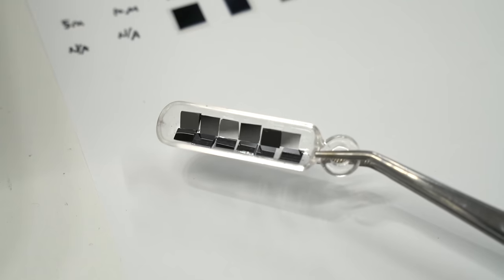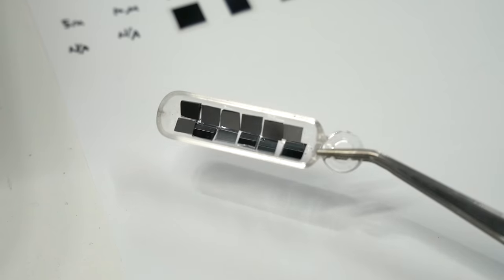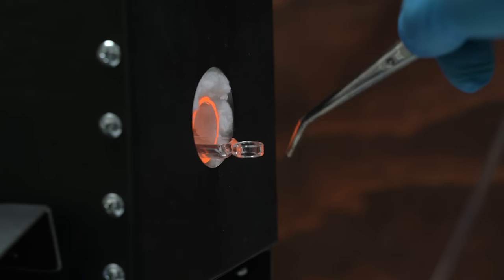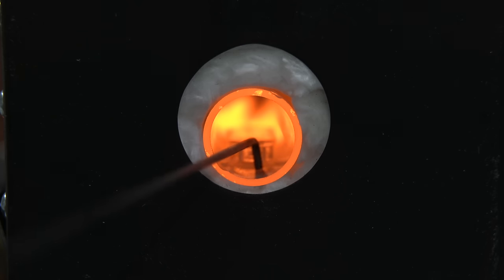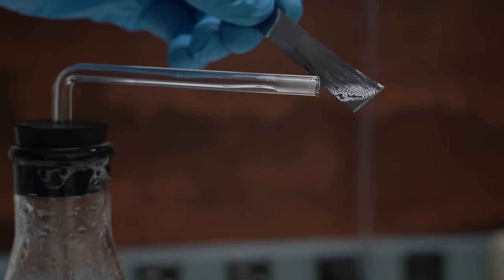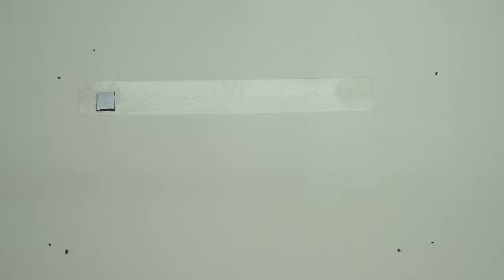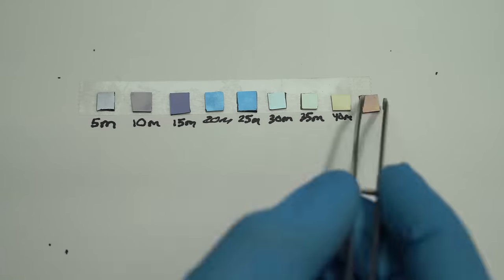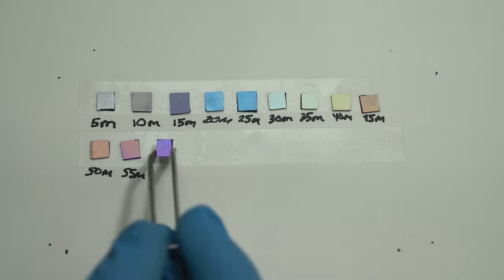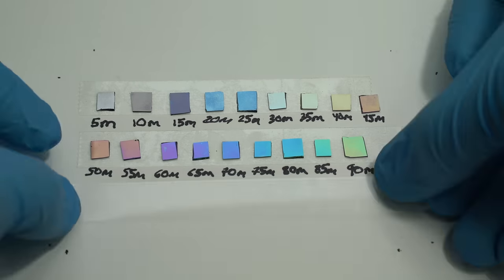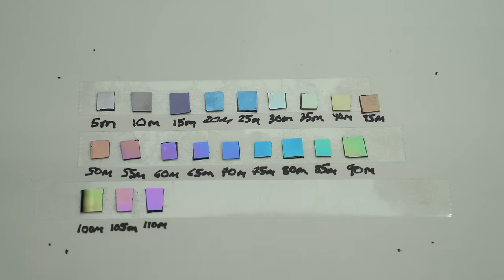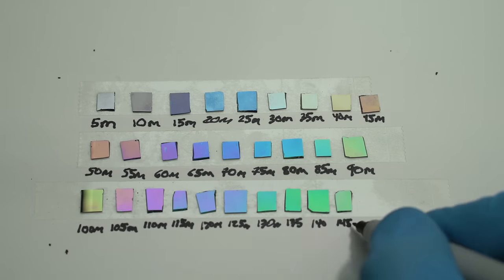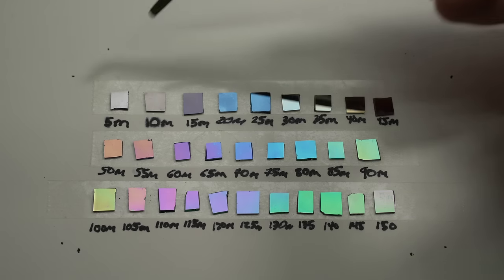I wanted to grow a bunch of different oxide thicknesses at once, so I put a bunch of tiny chips into my quartz boat and put them into the furnace at 1000 degrees C. It's important to get them directly in the center so that the temperature is accurate. I make sure the steam generator is working, and I insert the output tube into the furnace. Every 5 minutes, I take out one of the chips. I keep this up until I have a spectrum of thicknesses corresponding to growth times from 0 minutes all the way up to 150 minutes. Side note, 150 minutes is kind of a lie because I had to take the wafers out each time, which means that part of that 5 minute interval was spent heating the wafers back up to temperature, but don't worry about that for now.